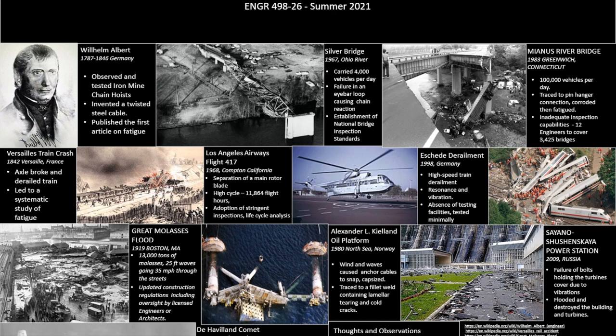Up at the top right, the Mianus River Bridge failed in 1983 in Greenwich, Connecticut. This bridge on I-95 carried 100,000 vehicles per day. Failure was traced to a pin hanger connection, which corroded and then caused a fatigue crack. At the time, there was inadequate inspection capability, with only 12 engineers to cover 3,425 bridges in the state.